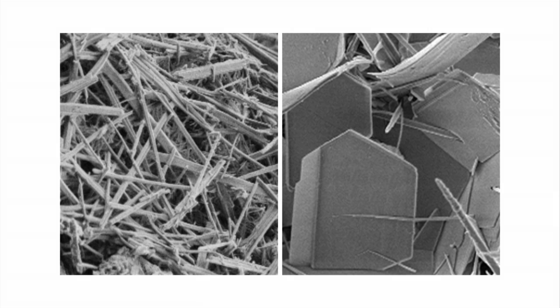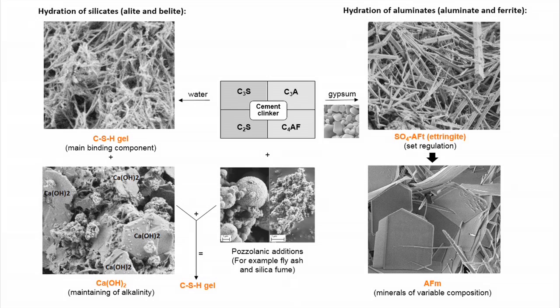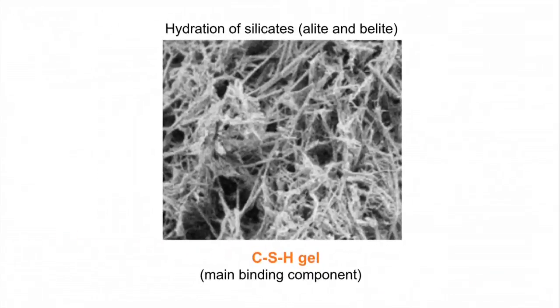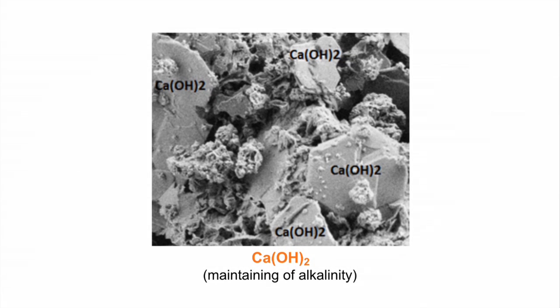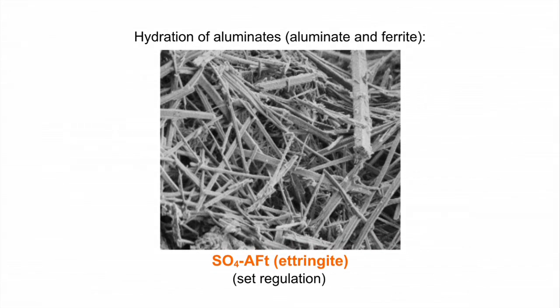Formed minerals can be observed only under the electron microscope because of their small size. In the hydration of silicate phases, alite and belite, CSH, calcium silicate hydrate gel, and calcium hydroxide are formed. CSH gel is the main component, which gives the binding properties to cement stone, and thus to concrete. Its morphology is unspecified. Calcium hydroxide appears as a crystal with characteristic morphology of hexagonal lamellae.